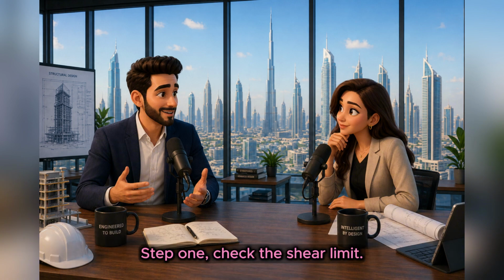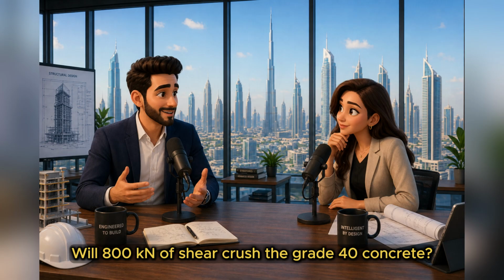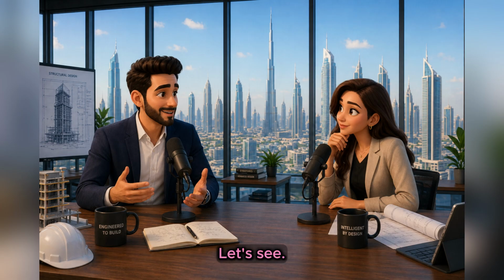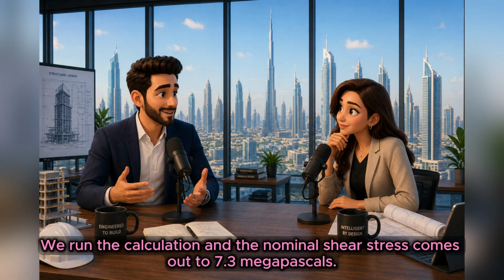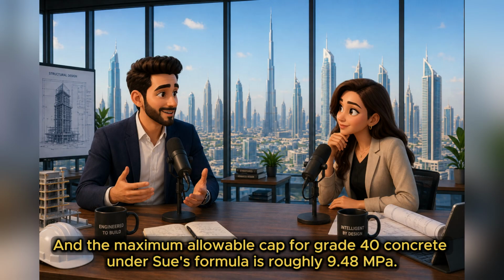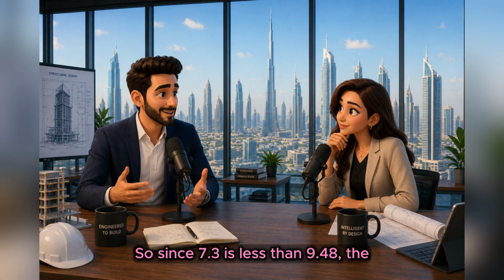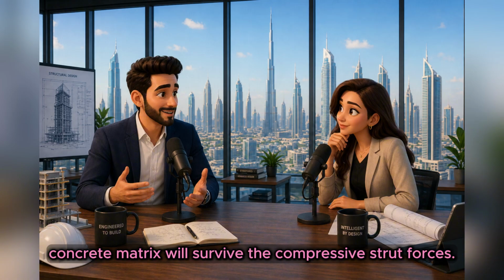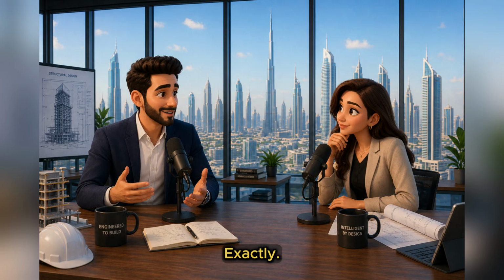Perfect. Step 1. Check the shear limit. Will 800 kilonewtons shear crush the grade 40 concrete? Let's see. We run the calculation, and the nominal shear stress comes out to 7.3 megapascals. And the maximum allowable cap for grade 40 concrete under Su's formula is roughly 9.48 MPa. So since 7.3 is less than 9.48, the concrete matrix will survive the compressive strut forces. We proceed.